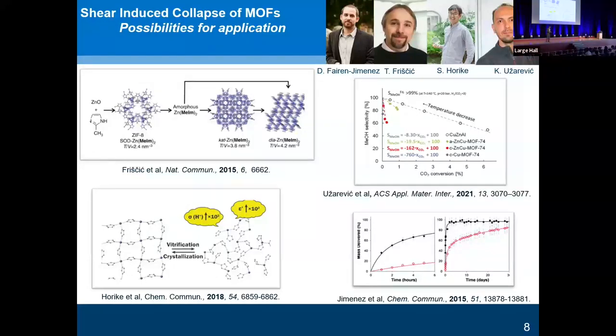Right? We can recrystallize these into different structures because our components are still there. Satoshi Horike over in Kyoto has done some beautiful work on ball milling coordination polymers, showing that when you ball mill them and form the amorphous equivalent, they actually have higher proton conductivities. Krunoslav Užarević over in Croatia has shown work on the catalytic ability in MOF-74 systems. So these MOF-74 systems are actually more catalytically active when you've amorphized them.